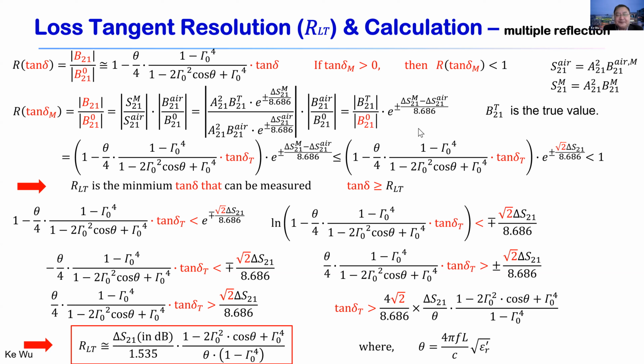So now let's look into this. I will not go through the detail of that. In the analytical formulas for the material parts, we develop the transmission equations from interface 1 to interface 2, and also for low loss materials. Those equations we developed. This ratio we called R. This ratio gave these equations, and those equations involve the loss tangent values. Of course, for the real materials, we can also develop the material aspects. This formula is similar to this one, but we developed it in an expanded way, for example. I will not discuss the detail of this expanded formula.